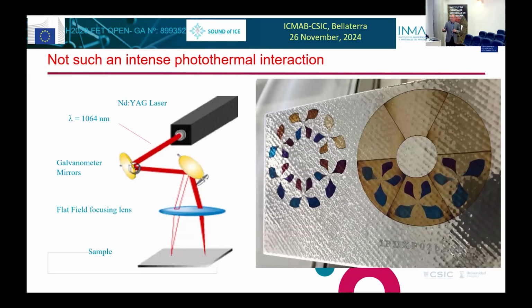You can take, for example, titanium deposited by PVD, that's just a few nanometers of titanium, on a glazed ceramic. And you can shine a sub-nanosecond laser and oxidize this titanium selectively. So make a thicker or thinner oxide and get one of these interference colors, which are permanent. And they are just solid. That means the color doesn't change depending on the angle of view. You don't know why I say that, but you will see why I say that later. So these are solid colors.